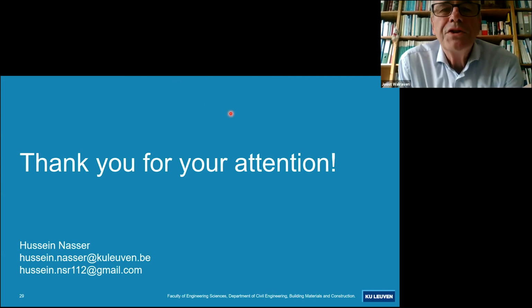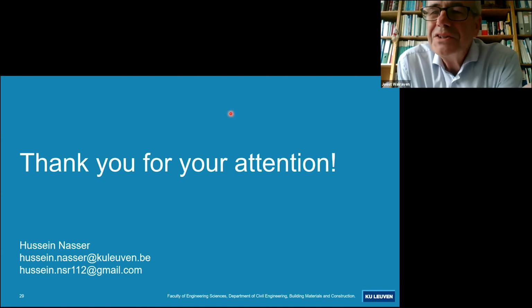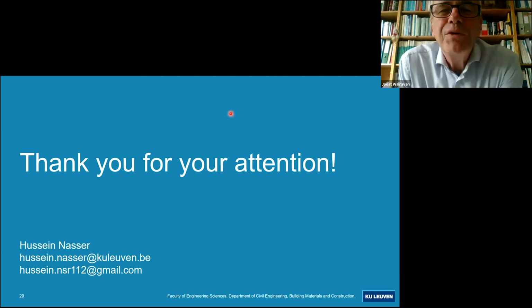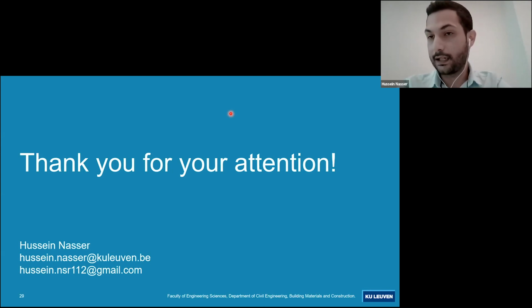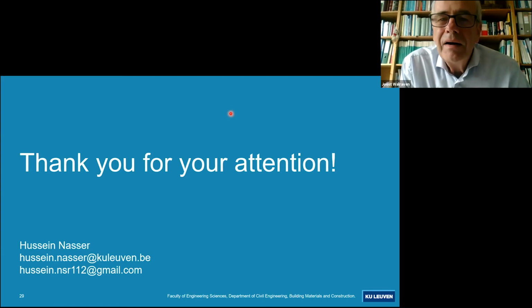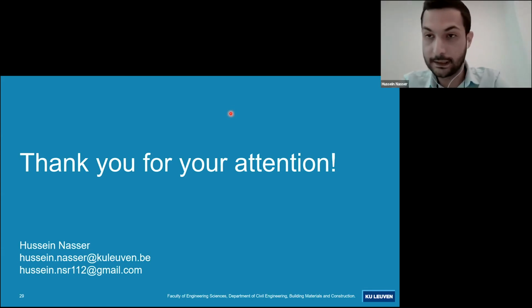What value of shear retention factor did you use? How sensitive are the numerical results for the 3-point bending test to that factor? It's about the same question that I raised. Yeah, I didn't test the sensitivity, but I used a value of 0.1, which is the default value. But I remember if I would increase the retention factor, the bending capacity would be overestimated. That's as I remember very well. So I stayed with the value beta equals 0.1 because it agreed well with the load deflection curves in terms of stiffness and yield bending capacity or yield point and the cracking behavior.